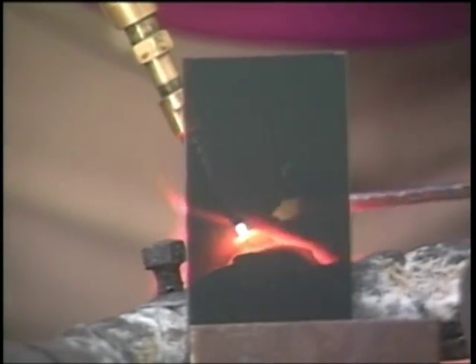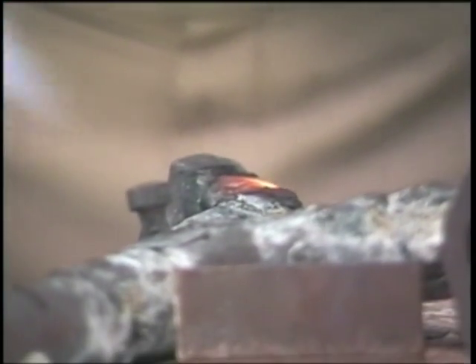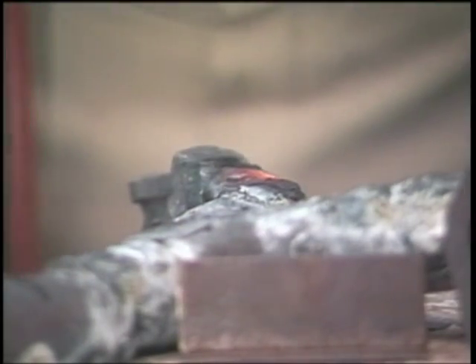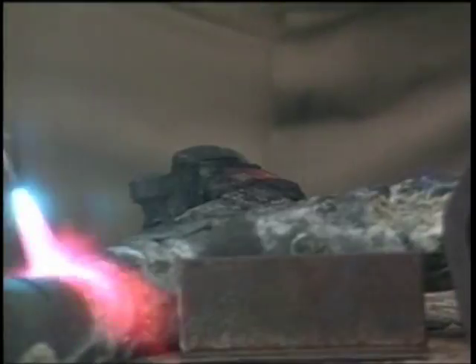Now every now and then we'll run across a real dirty piece. And every time you try and weld it, it looks like it don't want to flow real smooth. Go ahead and make that initial pass, trying to get it to flow as good as you can. It's just floating those impurities to the top. And usually by the time you go back over it, you can get it by that second or third pass on that extremely dirty stuff. As you can see right there, you can make pass after pass after pass and build it up. All right, so at this point right here, if you don't have an oven or a grill to put it back into, we're going to take our torch, cut the heat up. We're going to go back and post heat it.